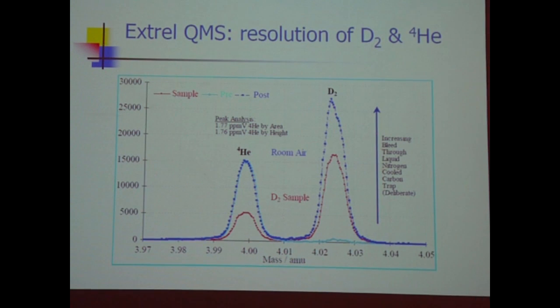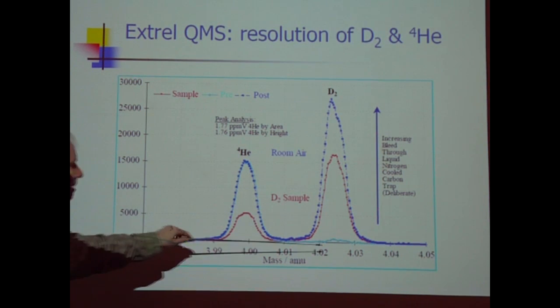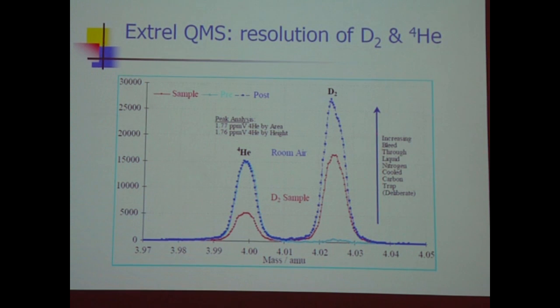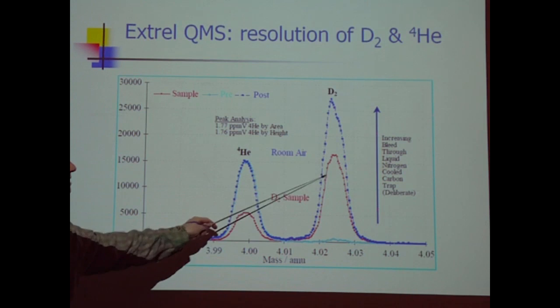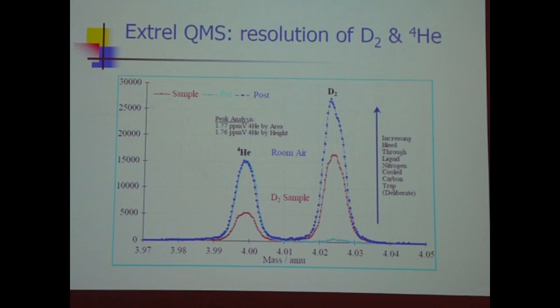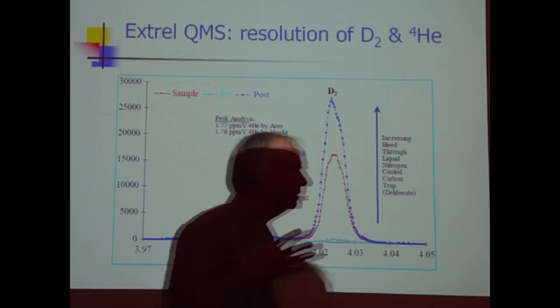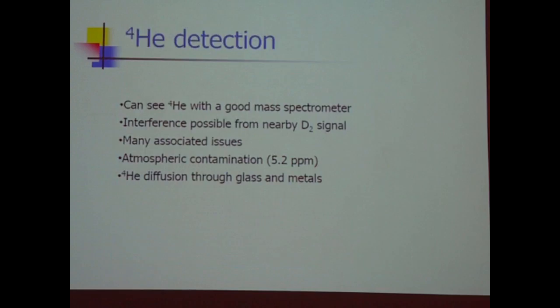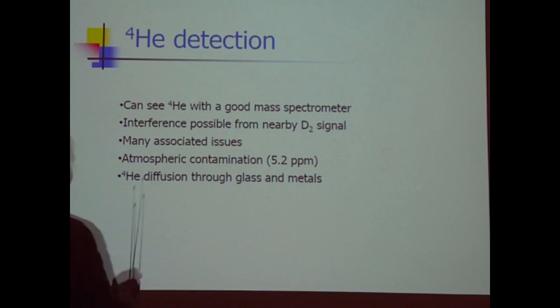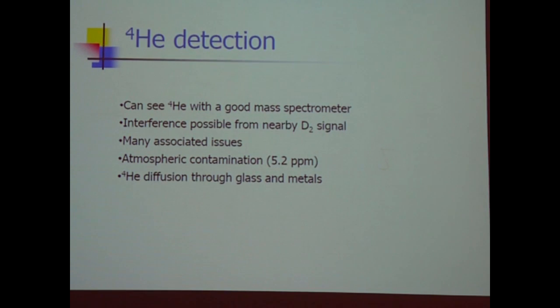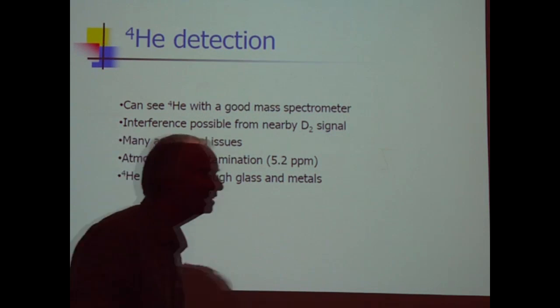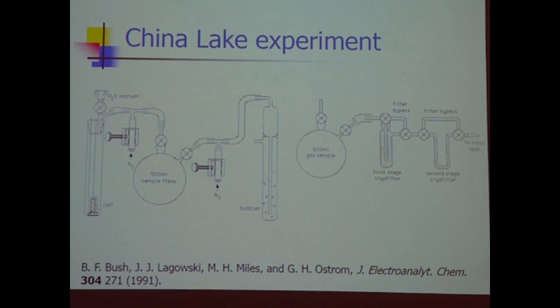To measure helium-4, you have a headache: helium-4 has a low mass. A little bit higher mass is D2, so you need a good mass spectrometer to separate the helium-4 from the D2. This is data shown under conditions where the amount of helium-4 and the amount of D2 are roughly commensurate. If your helium-4 is just a really tiny amount and you've got lots and lots of D2, then this gets really big, and this isn't going to show up if this guy's really big. So when you do your measurement, you have to reduce the amount of D2, so you need traps to make it work better. And anyway, you need a good mass spec, there's interference, lots of technical issues, atmospheric contamination. Also, helium-4 goes through metals and glass, which is what makes getting a helium-4 leak-tight system tough.